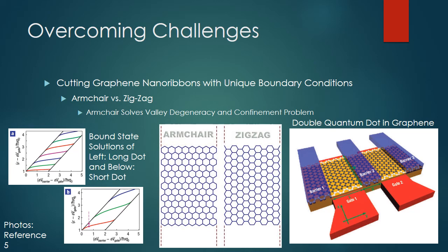They have also shown that by doing a slight modification to this architecture, the valley degeneracy can also be lifted. By terminating the edges of the nanoribbon with semiconducting armchair boundaries, the valley degeneracy is lifted. While this seems very simple, in practice it can be quite difficult to get nicely ordered boundaries. The diagram in the center of the slide shows the difference between armchair and zigzag boundaries. Notice the pattern of termination on the left and right sides of each ribbon.